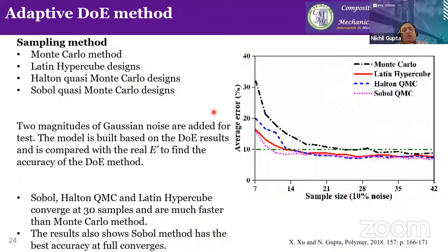And many of these sampling methods are now available. There's Monte Carlo, Latin Hypercube, Halton quasi Monte Carlo, or Sobol quasi Monte Carlo method. So these are more advanced methods than the particle swarm algorithm. But then here the trend that you see is that the average error reduces to less than 10% in most cases with as little as about 10 points. The Sobol is quite a powerful method in this case. With less than about 10 points, you can capture the data pretty nicely.